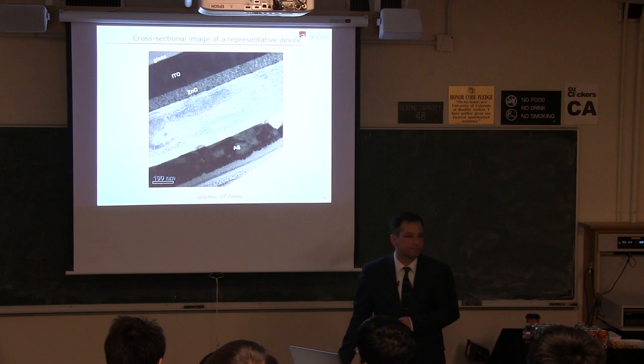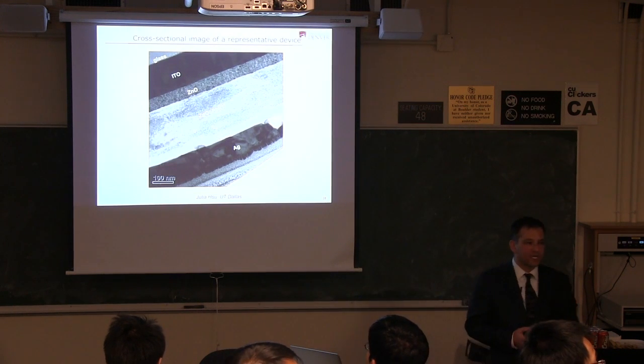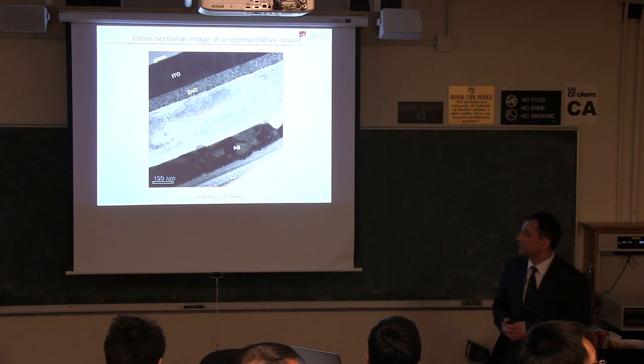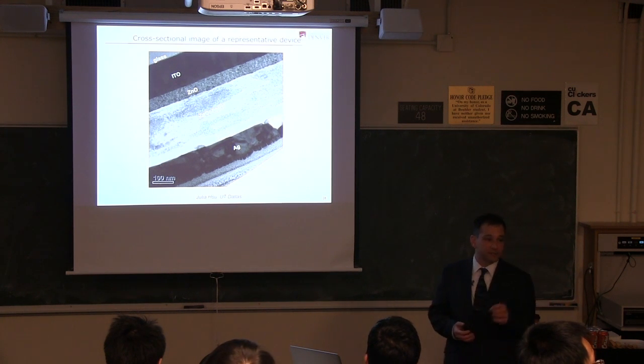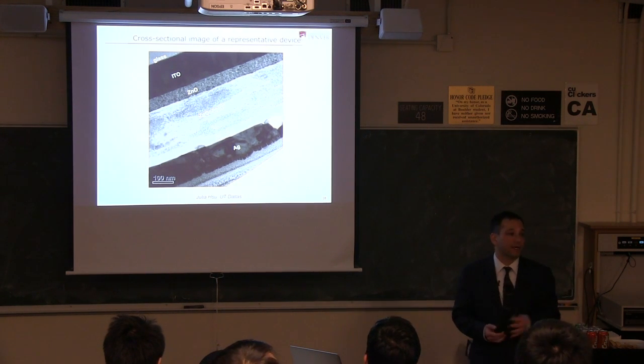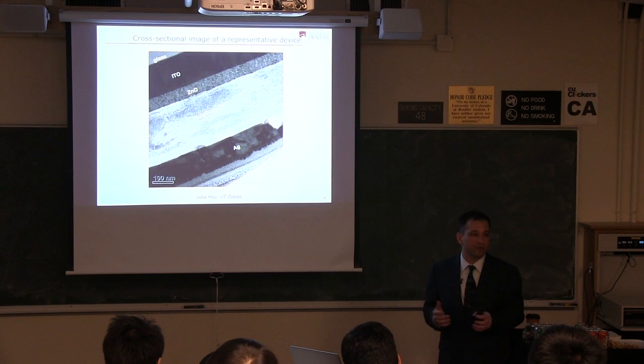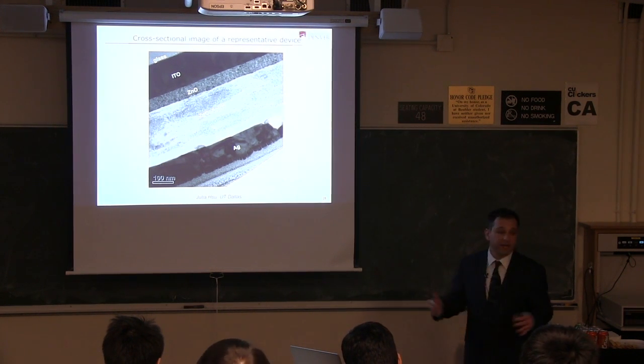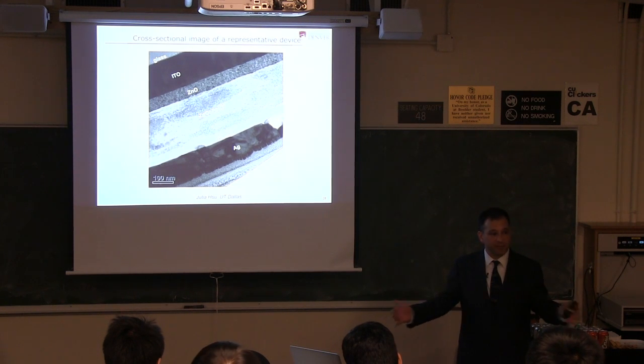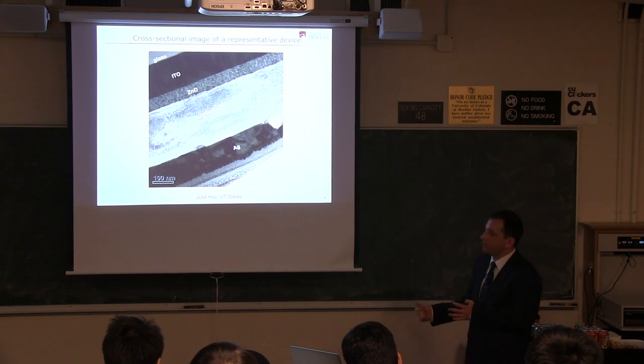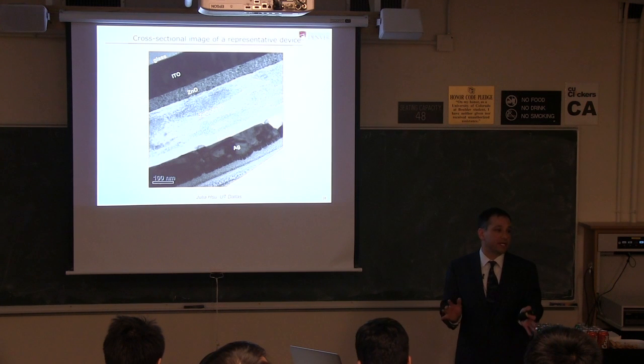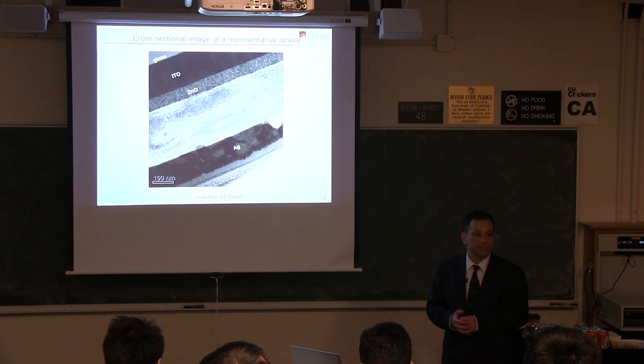The charges, they have to make their way across 100 nanometers. That's right. So the mu-tau product in the device, carrier mobility times lifetime, has got to be about 100 nanometers. That's right. Ballpark figure. Really depends on the material. So P3HT tends to have a much better mu-tau product. We can make it much thicker. A lot of the other materials, we have to make them as thin as 80, 90 nanometers to get the charges out. That's one of the big issues.